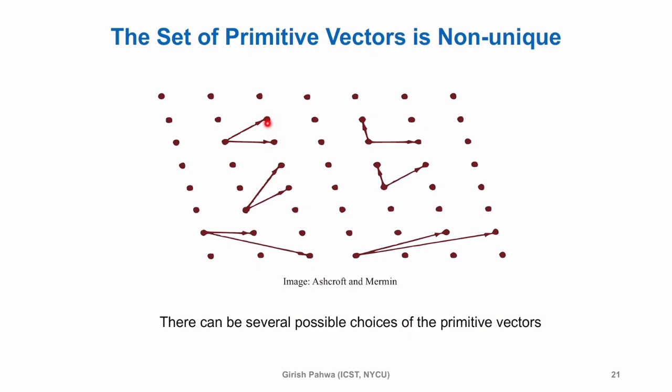This point is shared by 4 others, so this is going to keep repeating like this. So 1 point will be shared by 4 parallelograms. In total, the contribution of 1 point is just 1 by 4. So one smallest volume has 1 point. So this is again a property: the repeating volume, the smallest volume, will be the one which has only 1 point.